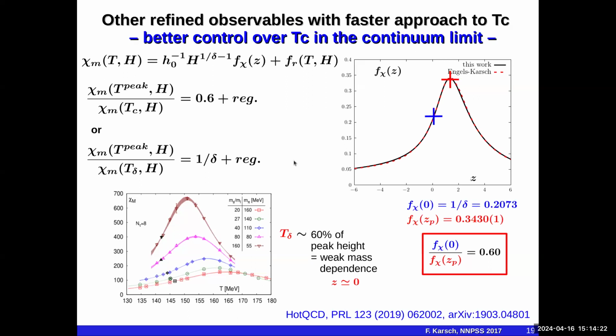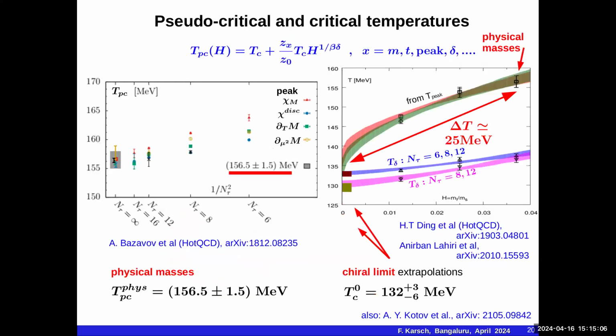for yet another set of pseudocritical temperatures, which I introduce in this figure here, in this slide here. So rather than using the peak of the susceptibility as a pseudocritical temperature, one uses susceptibilities at 60% of the peak height, which has the advantage that the quark mass dependence of these defined susceptibilities or pseudocritical temperatures is particularly weak and allows a quick extrapolation to the chiral limit. And that is shown here in the right-hand figure.